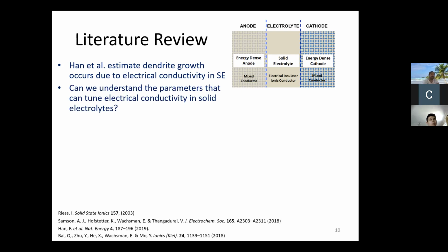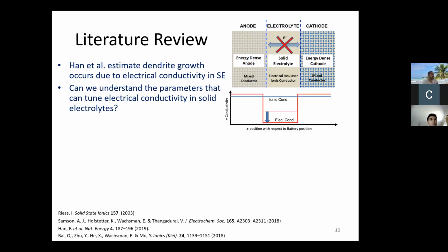One question that we'd like to look at is, can we understand the parameters that lead to electronic conductivity in these systems? Can we engineer or tune this electronic conductivity in the solid electrolyte, in particular, lower it? But we also have another question. In the region of the electrodes, we want it to be a good electronic conductor. So can we also tune it the other way? In this case, we just want to get a map where we can move around our tunability of where we want our electronic conductivity without hopefully affecting too much of the ionic conductivity.